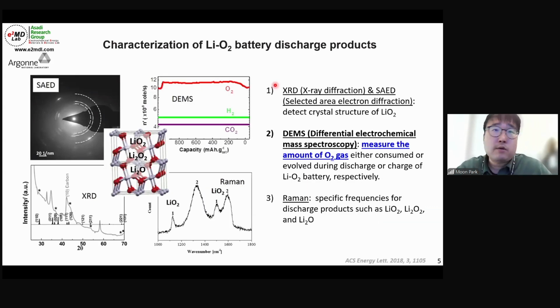So I'd like to introduce the characterization. What is the typical way to characterize the lithium discharge products that are formed in lithium-oxygen battery research? We can use electron diffraction and X-ray diffraction as long as the discharge products, such as lithium superoxide, peroxide, and lithium oxide, have crystallinity. But they could be amorphous as well. Regardless of whether they are crystalline or amorphous, DEMS and Raman can be used to detect the discharge products.